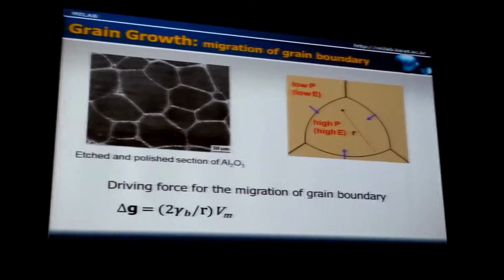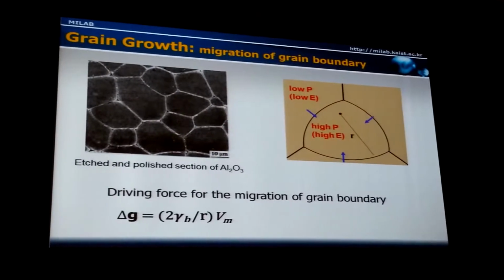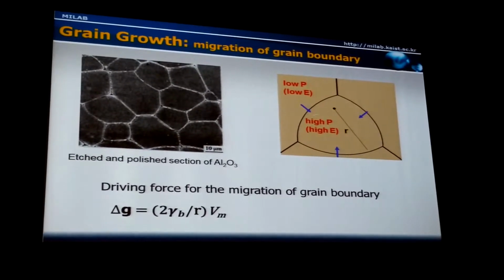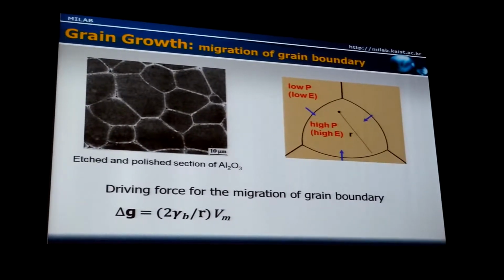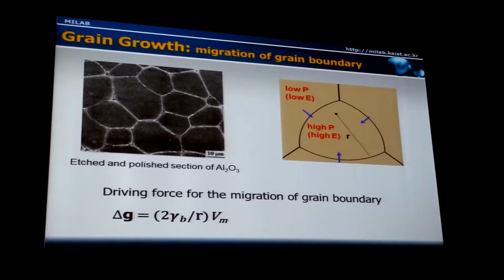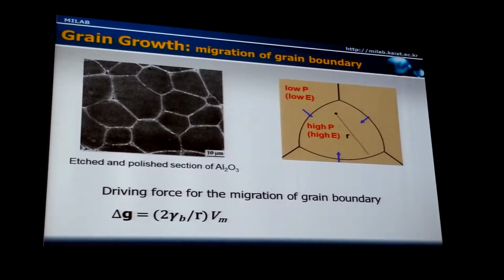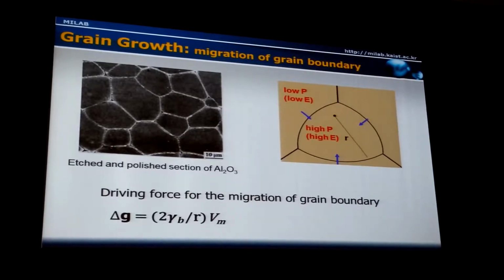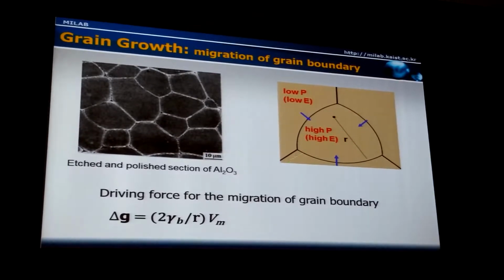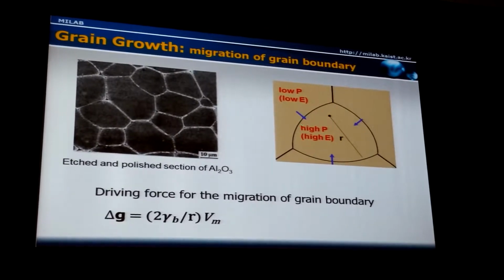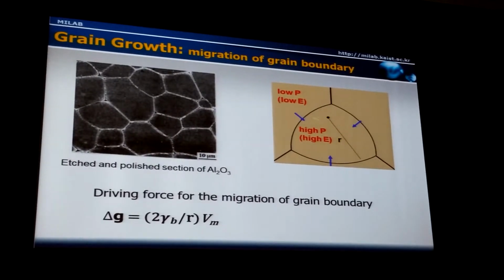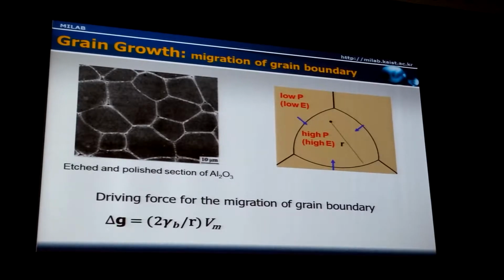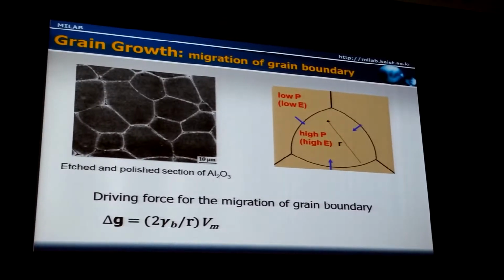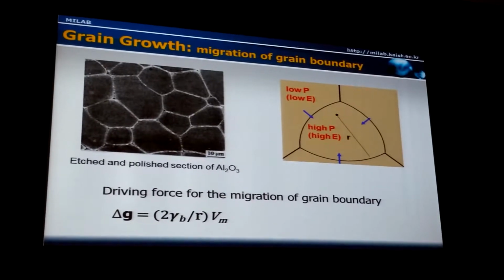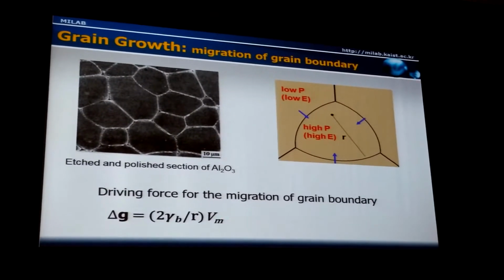The grain with a convex grain boundary has a high capillary pressure, and the grain with a concave grain boundary has a low capillary pressure. So there's a capillary pressure difference. Because of the difference in capillary pressure, there's a difference in energy and chemical potential. So the driving force for the migration of the boundary is, of course, the capillary energy, which can be expressed by this equation. And 2 gamma boundary over R is the capillary pressure difference between the two adjacent grains, and the other term is the molar volume.